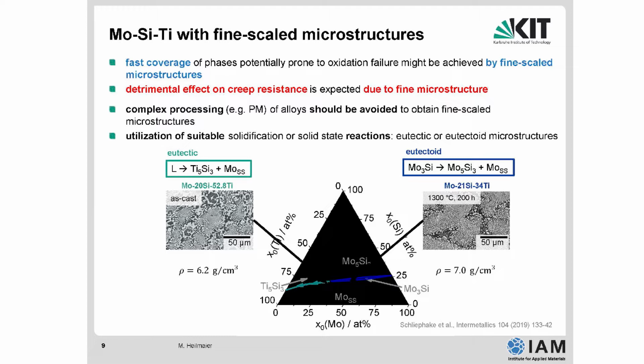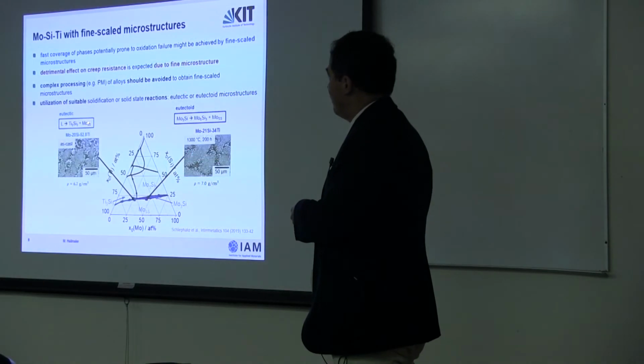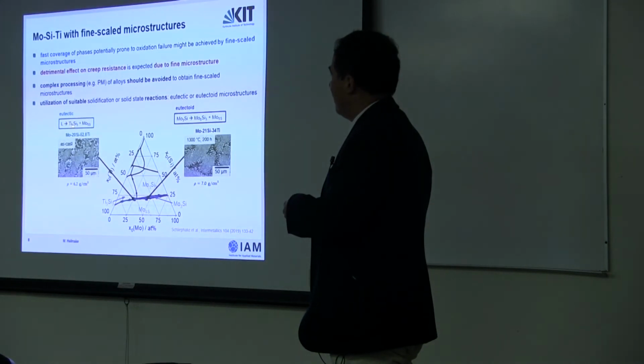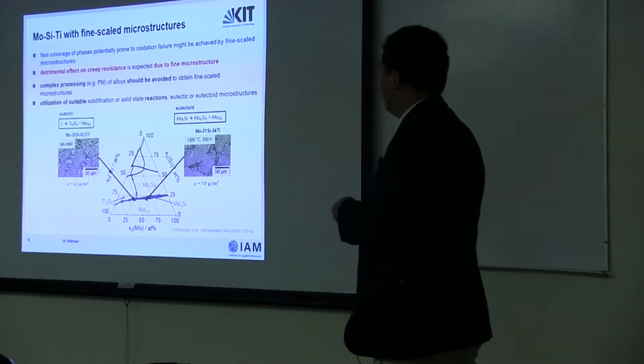Those here are not so much interesting because we don't want to go into very high silicon contents, and we don't want to go into low titanium and molybdenum contents, so we are interested in this part here. The green part, which gives you a eutectic reaction. Everybody should know what a eutectic reaction is. When you cool down a liquid, it phase separates into two solid phases. In this case, it's molybdenum solid solution, disordered, and an intermetallic compound of Ti5Si3, the one I mentioned on the previous slide.